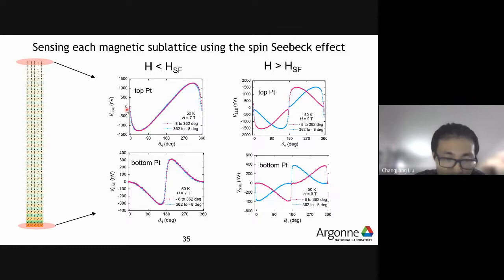Then we found that in the top layer, the platinum layer shows a specific Seebeck voltage with different polarity than that measured at the bottom surface. You see that the maximum here occurs at an angle close to 0 degrees rather than 180 degrees. So basically, they show opposite behavior. This is just because these two sublattices initially have different orientations, so they have opposite responses to the external field. And this is also true for the field above the spin-flop transition.